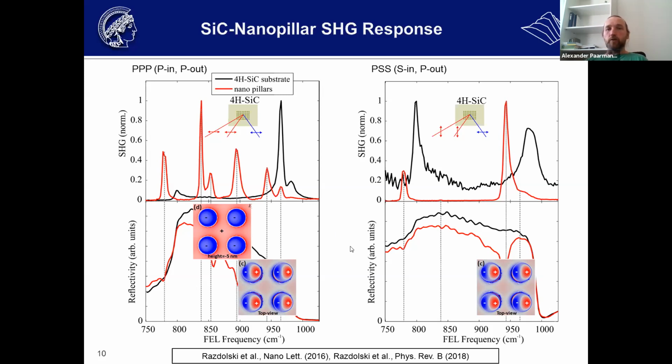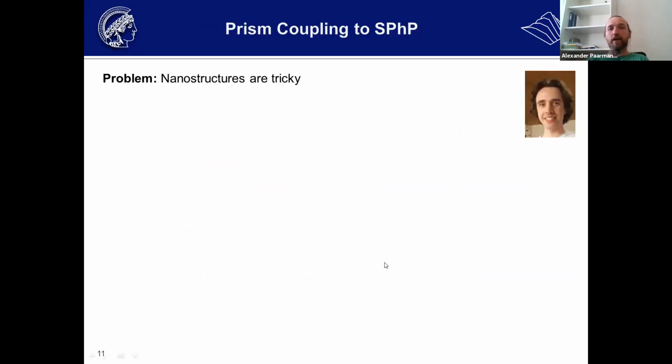The grain of salt for me for this study was I went in hoping that we can actually quantify, put numbers on, so that there's a calculation. Now we have an experiment that can probe that. Can we actually quantify experimentally the magnitude of these optical field enhancements? And basically we had to come to the conclusion that we can't, mostly because you have these inhomogeneous field distributions because of the shape of the mode in these nanostructures, and you don't know enough with the far field experiment to recapture the actual amplitude. So this was my hope, but it didn't really work.